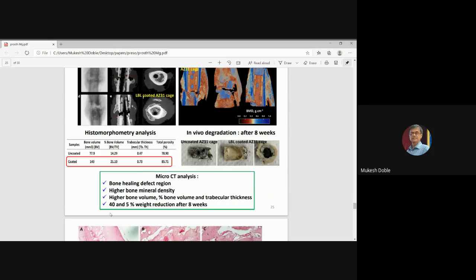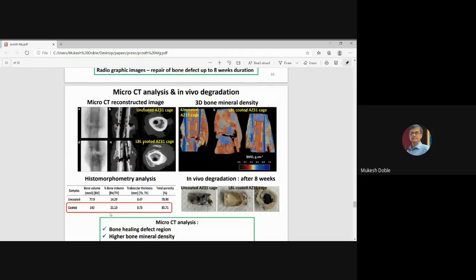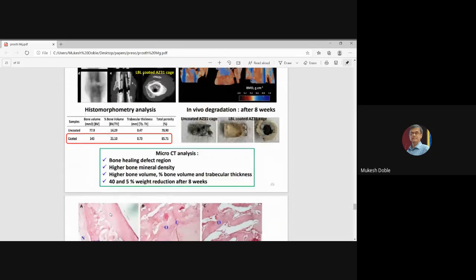So the coating has helped in increasing the bone volume, percentage bone volume, healing in 8 weeks. It has improved the porosity. At the same time, it's reduced the degradation of the magnesium cage, because the magnesium cage is the main thing which keeps the load in action. When compared to the uncoated surface, we see a lot of improvement in the polymer coated surface, actually. So higher bone mineral density, higher bone volume, as well as percentage bone volume.